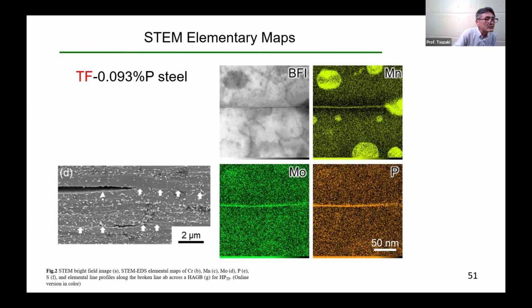Grain boundary segregation of manganese, moly, and phosphorus are clearly shown. I believe it is clear that phosphorus segregation at the grain boundary is related to delamination fracture because of loss of cohesion. However, the effect of moly and manganese segregation are still under discussion.